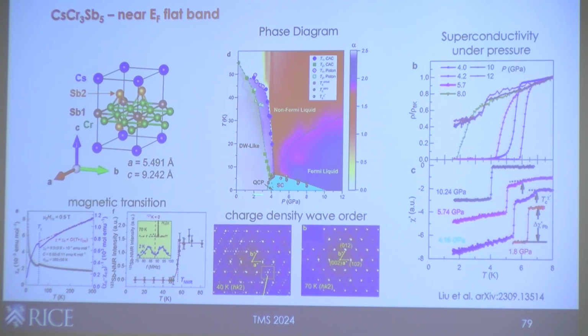What's really interesting is that under hydrostatic pressure, these density wave-like transitions are suppressed, and at some point they split, and when they're suppressed, you see the emergence of a superconducting dome, right? This is very reminiscent of all the unconventional superconductors we have encountered: the pnictides, the cuprates, heavy fermions, and so on and so forth. The other interesting thing, especially after Eric's talk, is that when the authors measure the resistivity and look at this alpha, the power law exponent, there is a large region of non-Fermi liquid behavior, which seems to emanate from here, right? This is starting to look like a quantum critical point in the dome.